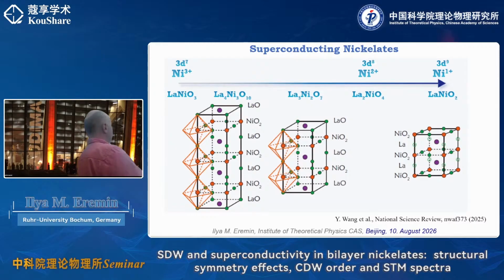However, the particular surprise system is 327. If you look at the oxidation of this Ruddlesden-Popper, this would be a single layer, which has been known for many years to be a magnetic insulator, and this one was not really well explored because of the complication of its synthesis, which still continues to be an experimental challenge, as I will tell you in a few minutes. If you compare the oxidation to the perovskite structure, you will realize that this is exactly in between. So it's 2.5.